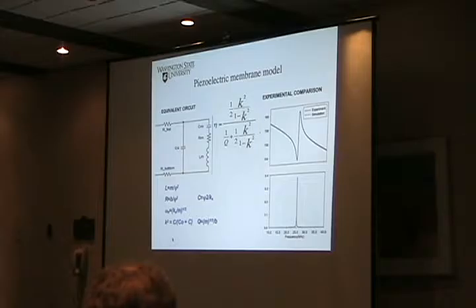So then we wanted to look at the efficiency of an oscillating piezoelectric membrane that we're forcing. We'd like to force this at the resonant frequency of the cavity which has the fluid and vapor in it. The first thing I'll point out is that the numbers I use for Q, I'm not missing a K or an M. I'm going to use numbers like 20. Not 20,000, not 20 meg, just 20. It's because this cavity has a bunch of fluid. We have a lot of dissipative mechanisms within the cavity that will hurt our Q in the device. But we have K squared, the piezoelectric electromechanical coupling, and Q, the resonant Q of the engine itself. We can test these things in a vacuum, measure relatively high resonant frequencies, and measure relatively good Qs. Later on, we'll be testing them with a bunch of fluid behind it, which will drop the frequency down somewhere around here and make the Q look something like this.